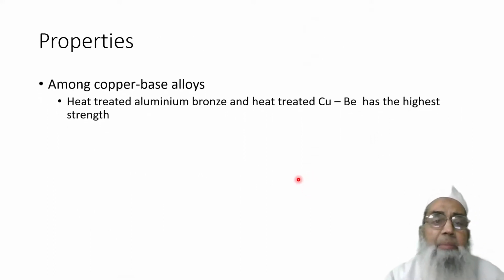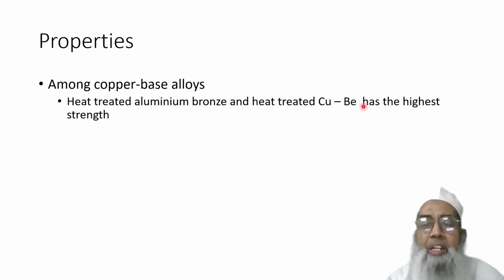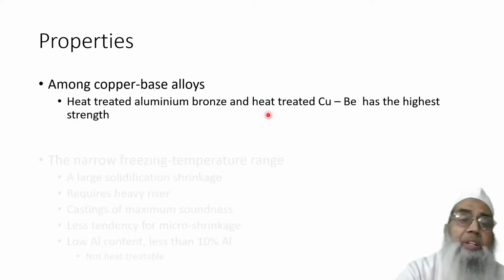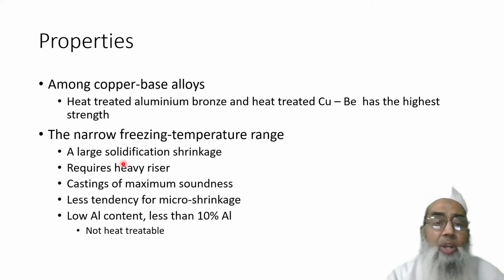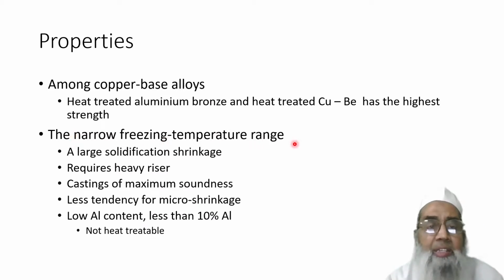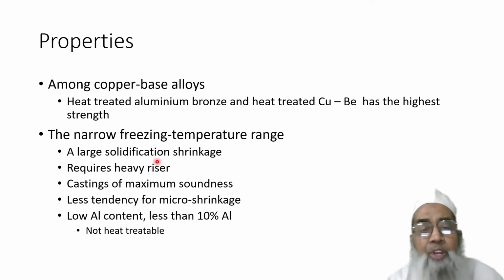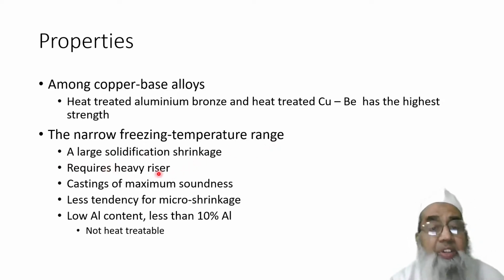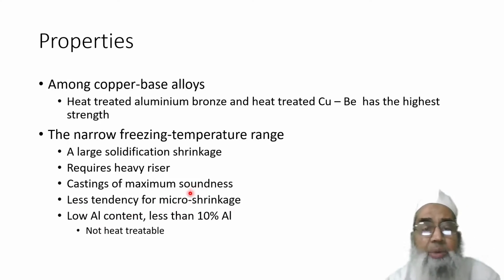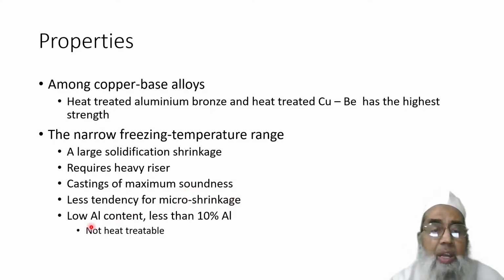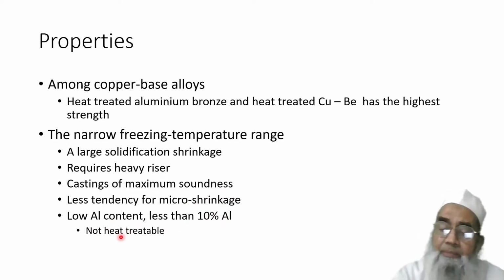Now therefore, among copper-based alloys, heat treated aluminum bronze and heat treated copper beryllium have the highest strength, and accordingly they have a lot of applications. The narrow freezing temperature range we have seen in the first diagram is very narrow, and therefore large solidification shrinkage requires heavy risers and gives casting of maximum soundness. Less tendency, because that short range gives less tendency to micro shrinkage. Low aluminum content, less than 10% aluminium, cannot be heat treated.